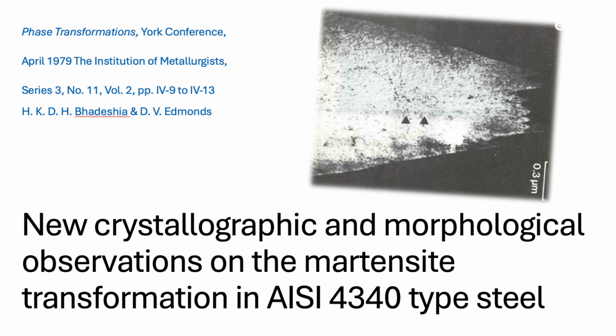The habit plane. Remind us what that means again. It's not just any boundary. No, definitely not. It's a very specific crystallographic interface. It's the plane where the parent austenite and the new martensite lattice meet with the least possible mismatch, the lowest strain energy. The path of least resistance, atomically speaking. Precisely. So the laths within a packet align along these low-energy habit planes, which strongly suggests they formed cooperatively.